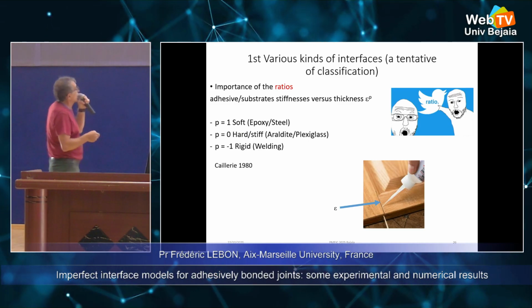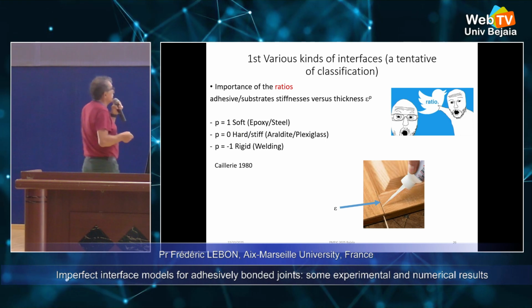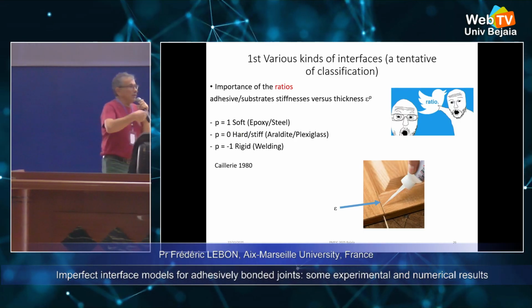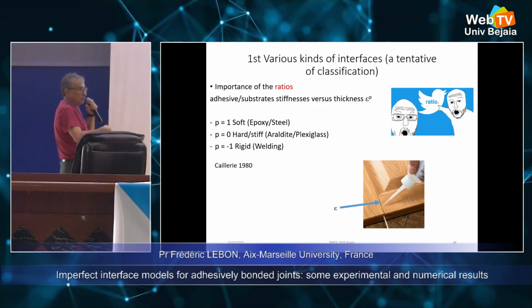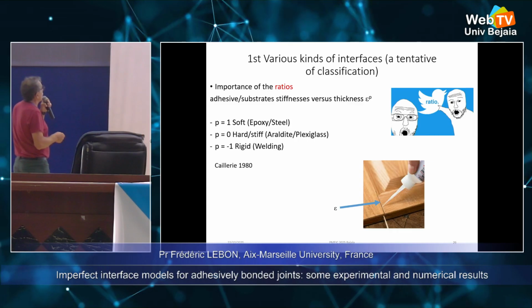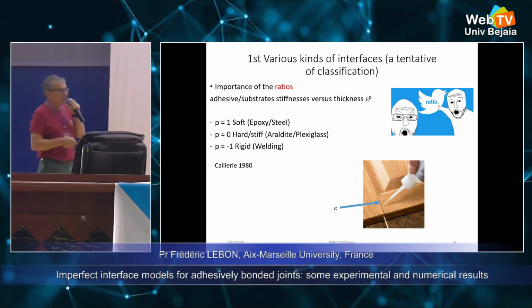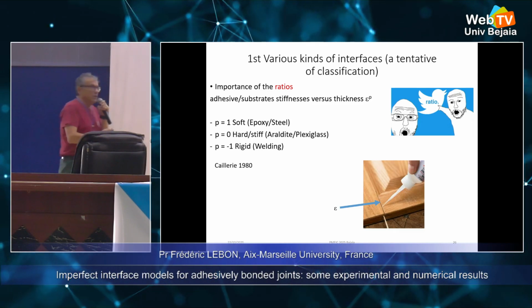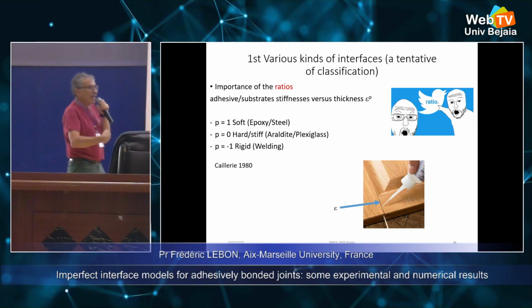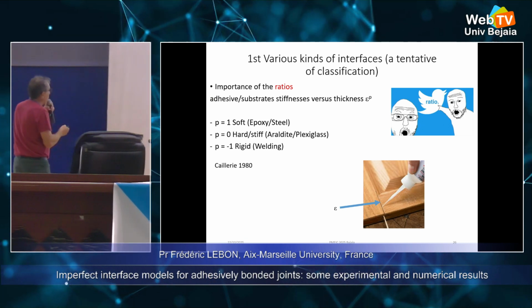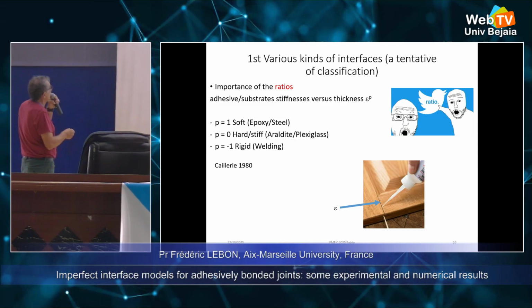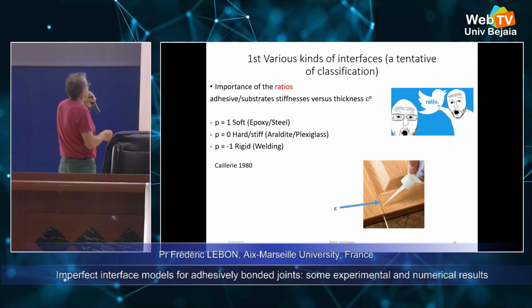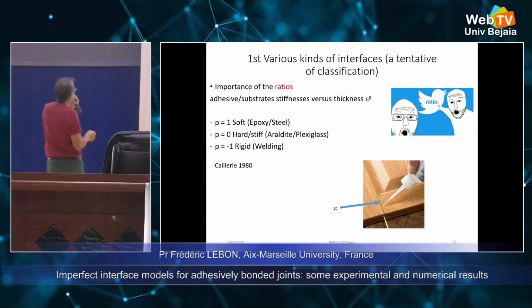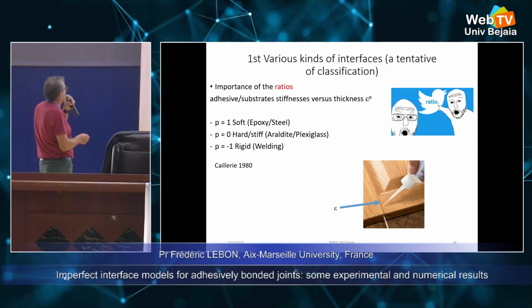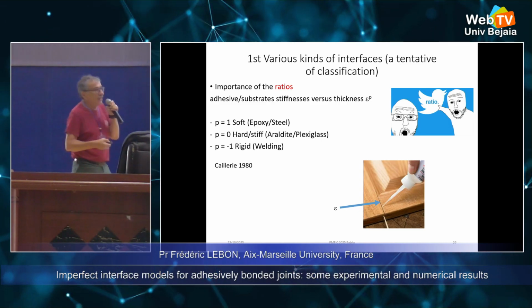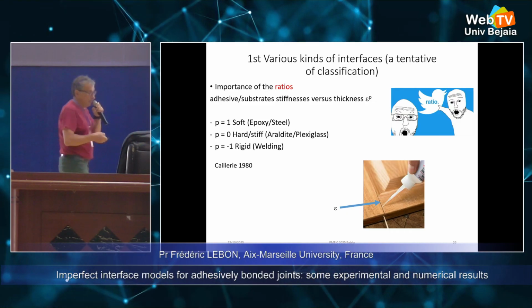There are different kinds of interfaces. This is a tentative classification. In fact, what is important is the ratio between the stiffness of the glue and the stiffness of the adherent versus the thickness. So, in the case, for example, we want to use araldite and to bond plexiglass, in fact, the stiffness of the araldite and the stiffness of the plexiglass have the same order. So P is equal to 0. In the case we want to bond two pieces of steel with epoxy, the epoxy is less stiff than the steel, and so in this case P is equal to 1. We have a soft interface. And it is possible for the welding to have P equal to minus 1. That is to say that the glue, in fact, is more rigid than the material.